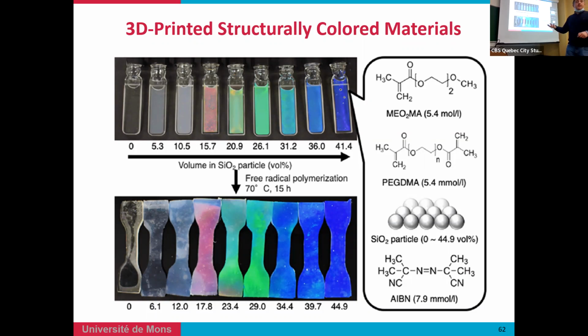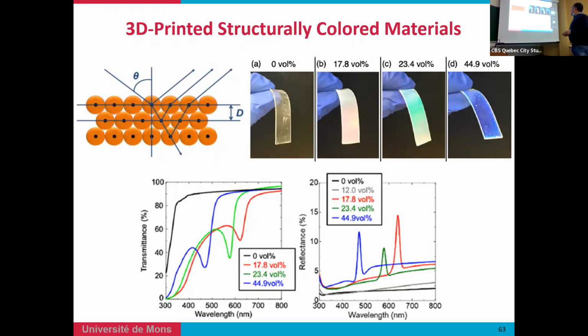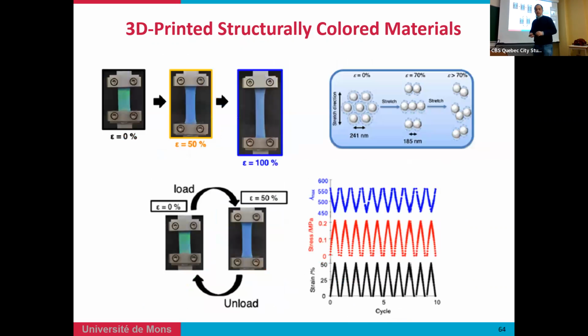What is very interesting is that when you take the gel and do the polymerization, in this case a free radical polymerization using temperature, you can see that the coloration you obtain is maintained after polymerization. You maintain, in fact, the system after polymerization, and this is based, as already mentioned, on the diffraction wavelength, as shown here. You can control the coloration depending on the content.